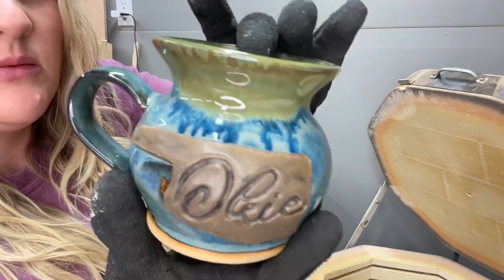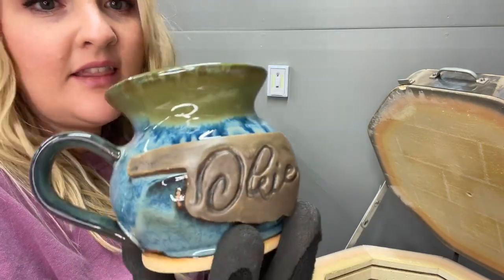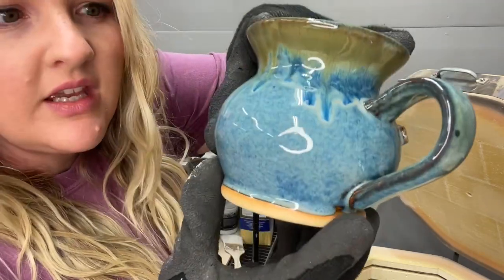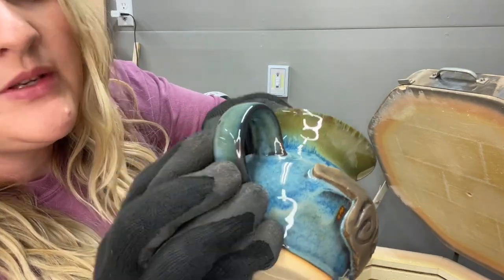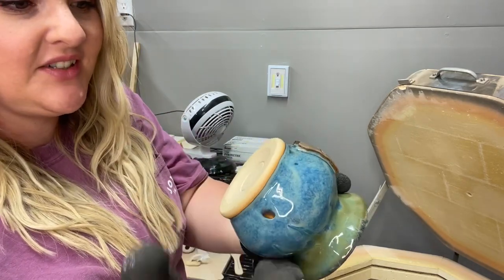This was a three-second dip in that really thick glaze. My seaweed is brush-on seaweed, but I poured two gallons into a two-gallon bucket so I could dip the rim — I didn't add any water to it. Just dipping the rim in that brush-on Seaweed honestly looks great. The stone denim blue was just too thick — it crawled there and there's one little pinhole — but honestly it does not look nearly as bad as I thought. This is still a good cup with no crawling inside.